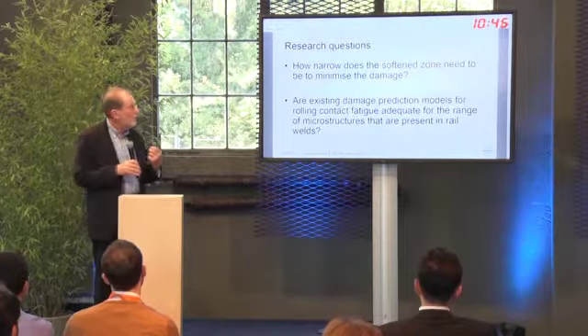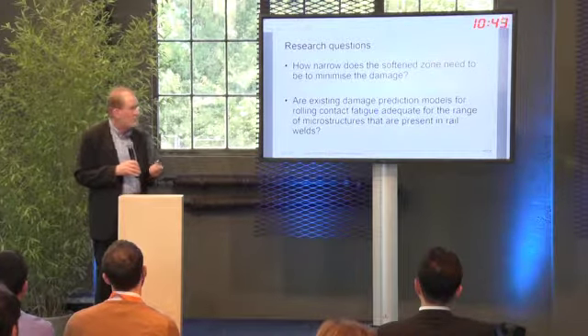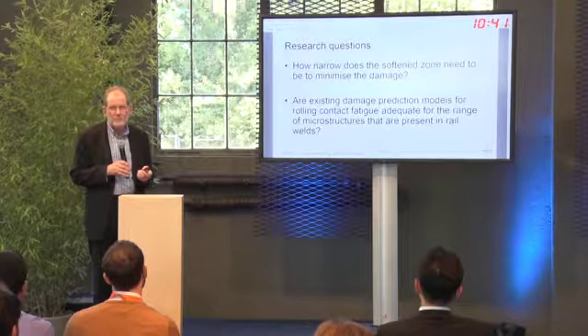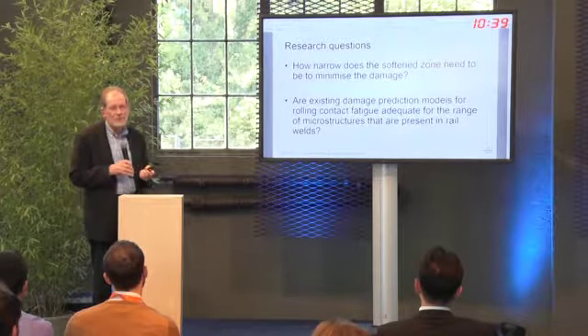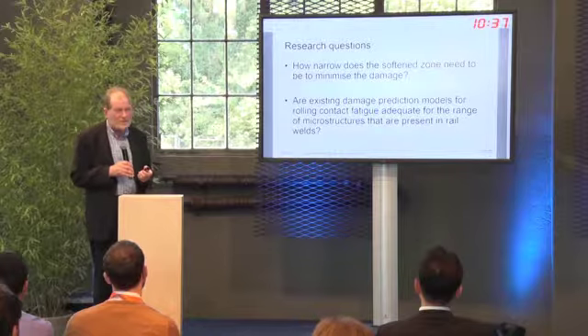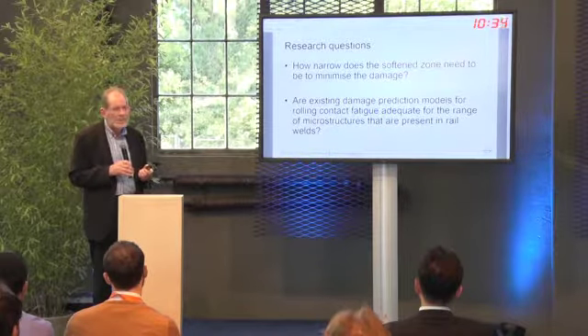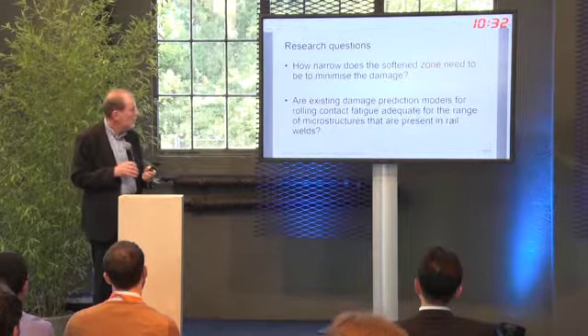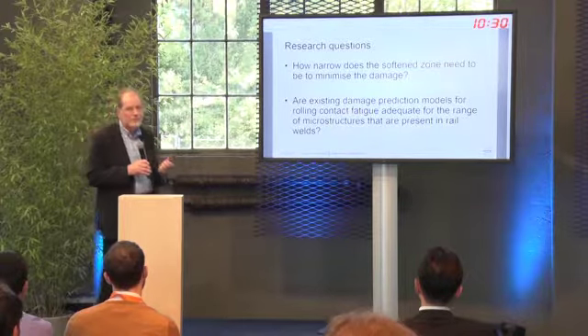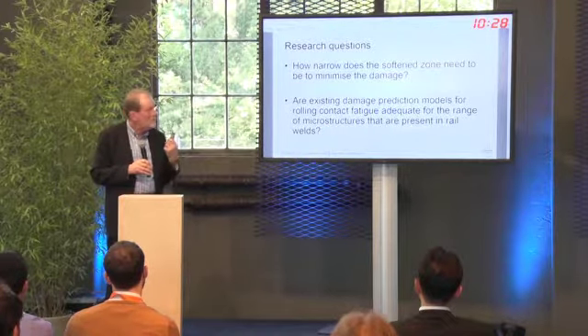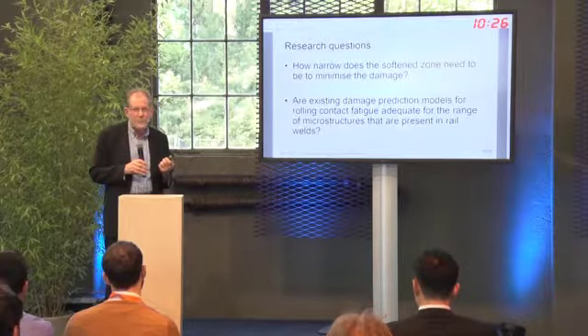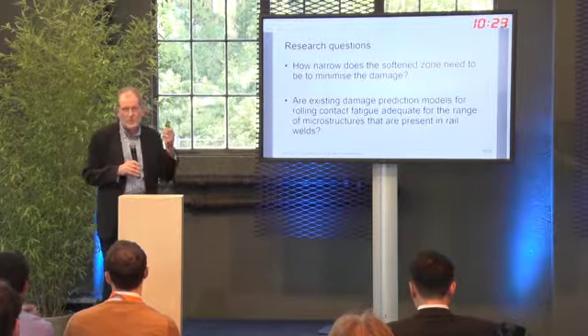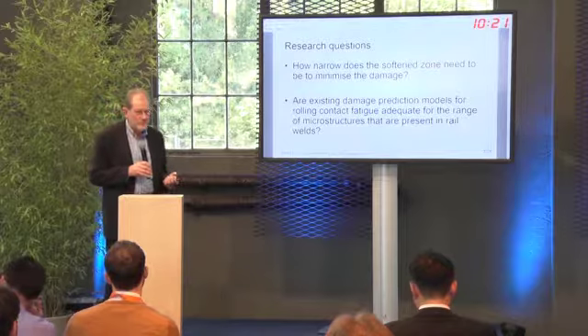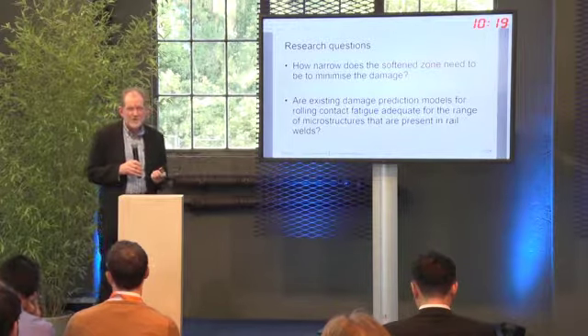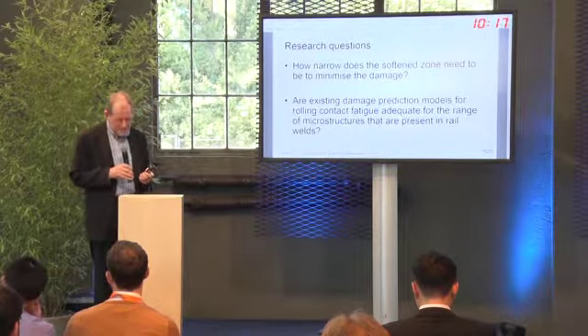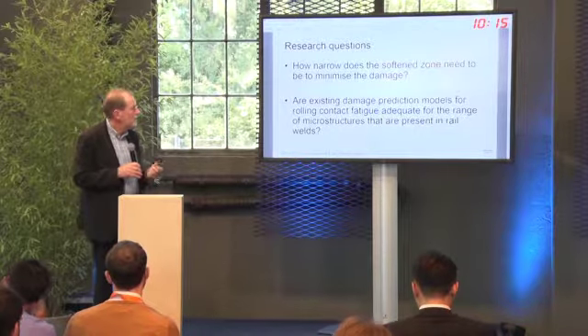So I guess two of the questions that come out of this were, well, if we're going to make the heat affected zones narrower, how narrow do they need to be to minimise the damage? And that's obviously the way we would like to go. One of the reasons for the concern about trying to make narrower welds is that the residual stresses in the welds will typically go up. So there's a risk of some pretty nasty fatigue failures in flashbutt welds if your residual stresses go up.